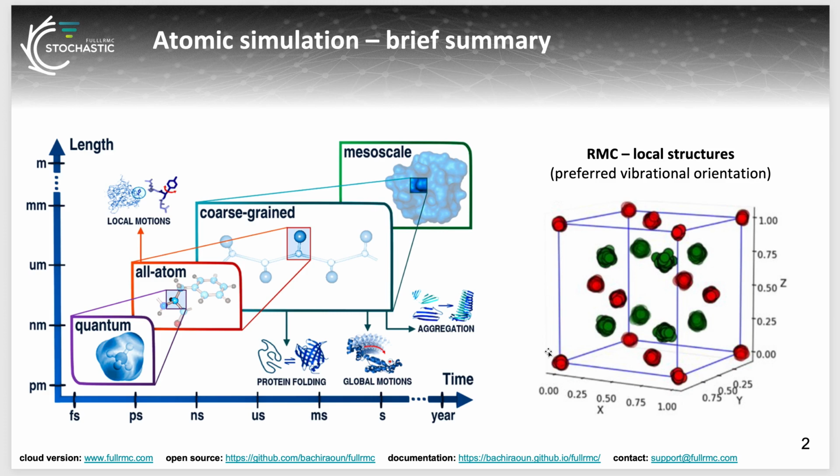This is proved to be a fine technique when the goal is to reproduce local structures and perturbations due, for example, to asymmetric atomic vibrations or orientations. Nevertheless, RMC suffers from the lack of uniqueness and is very limited in its power due to the nature of trying to find a complex solution by merely relying on random sampling.